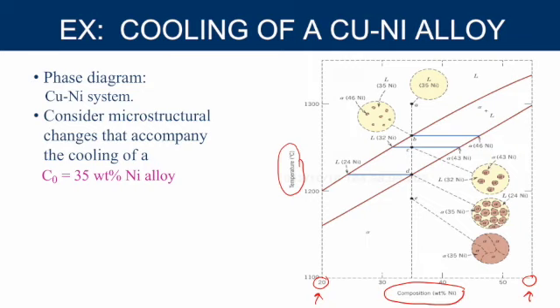So this is just kind of a zoom in on the copper nickel. We're only looking from 20 to about 55. Right, so you need to be able to read the spacing of the x-axis and the y-axis and understand the ranges that you're looking at. So we're only looking at a range from 1100 to about 1350 degrees and a weight fraction of nickel from 20 to 55. Okay, that's just so we can zoom in and see. So what's actually happening to the material? Let's start with the liquid phase. Okay, we've heated up to, in this case, about 35 weight percent.